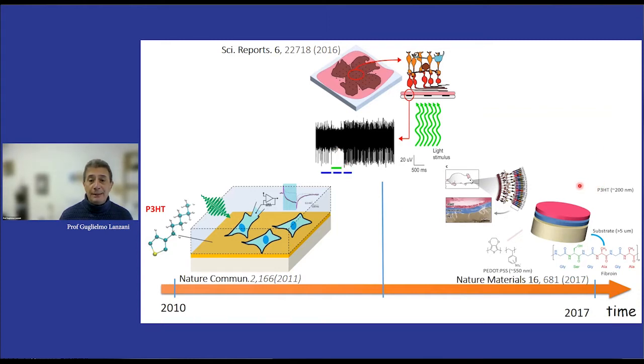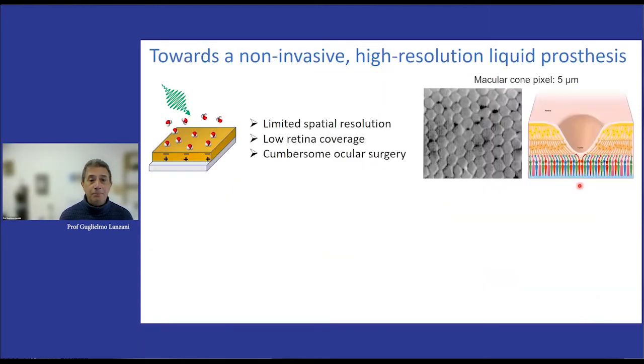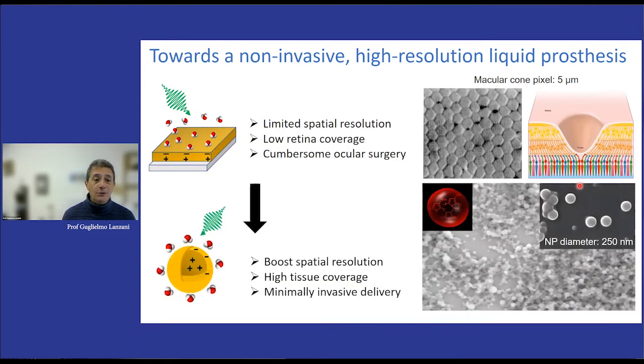From this, we went to the planar interface, which is made of silk as a substrate, which we implanted in the animal. Now, in spite of having good results, I should say that the surgery was rather cumbersome and the output yield was not very high with this kind of surgery. We had to implant the whole object, which is large like a stamp, a few millimeters square, might be smaller than a stamp, but anyway, the surgery was difficult. The coverage of the retina was small, and also the spatial resolution was apparently not very good. So we decided to move from this to another approach, which is the use of nanoparticles.